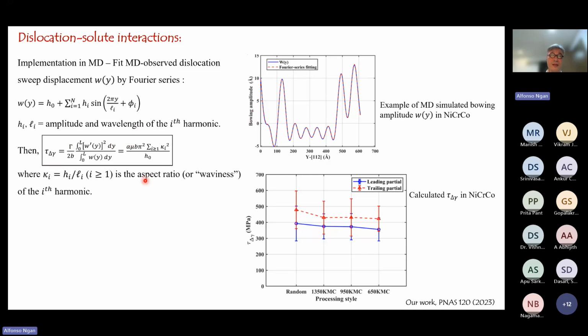We'll then be able to show that the equation just now can be obtained by this thing on the right, and that will enable us to calculate the strengthening due to the fluctuating fault energy. In this particular alloy that we were looking at, that stress term turns out to be 400 to 500 megapascal for different alloy conditions. This is for the random state, and these are annealed where some short-range ordering has developed. So in this case, the strengthening due to the fluctuating gamma is pretty constant, pretty independent of the alloy state.